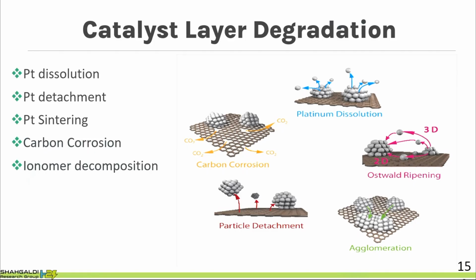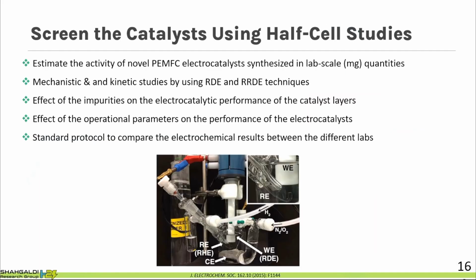Okay, but our catalyst layer, when we start running and using fuel cells and electrolyzers, goes through different degradation modes. So it doesn't mean that we can run forever with that catalyst layer. Sometimes we have platinum dissolution, sometimes platinum detachment, platinum sintering, carbon corrosion, ionomer decomposition. And we need to address all of these challenges in order to prevent the degradation of our catalyst layer.